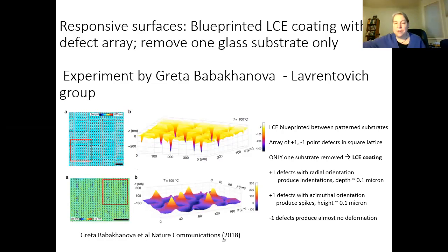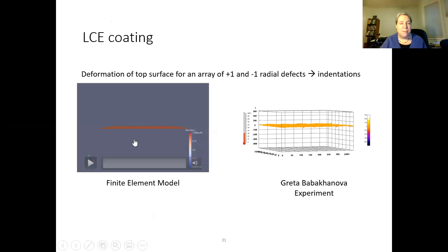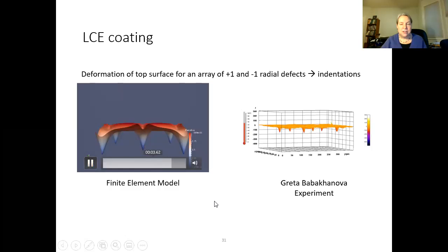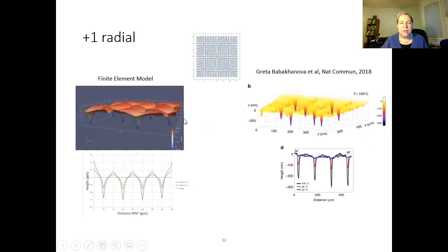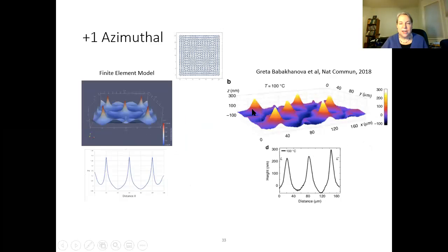So it's a programmable coating now. And here's an example of how the finite element model compares to the experiment. You can see the little dimples growing. So now we can start engineering coatings that are responsive to whatever kind of stimulus. It could be temperature, it could be light, various things. And we can have dimples, we can have spikes. Again, this is experiments, this is the simulation, this is what the actual microstructure of the thin film looks like. In this case, the director orientation is uniform through the thickness, and these coatings that have this interesting pattern we're fabricating using the MetaMask technique developed by Chi-Ho Wei, then at Kent State.